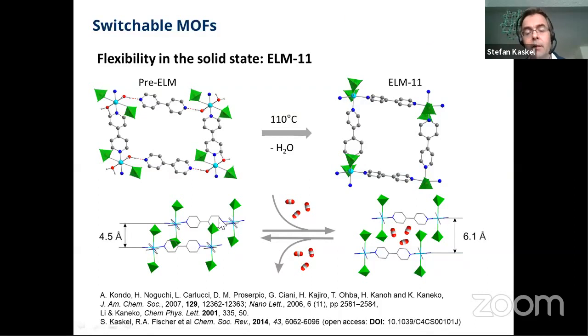And when you look from the side on this type of network, you can see that this is a layered structure. So one layer and another layer here. And the green tetrahedron here is basically a BF4 minus anion, which is coordinated on top and on the bottom of the layer. And these BF4 minus anions are blocking the pores. So this one is blocking the pore of the lower one here. So they are directed into the pores. And with a gas molecule, CO2 or methane or butane, depending on the temperature, then the layers are expanded.